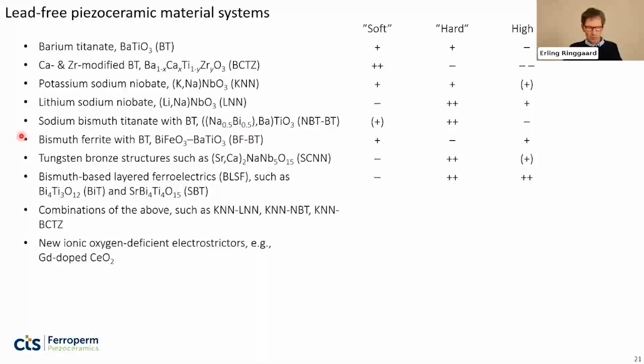Another interesting material is bismuth ferrite, also generally used in a solid solution with barium titanate, and I write it like this. Next material is not so well known. It's developed in Japan. It's a group of materials called the tungsten bronze structures, and one example is mentioned here. This is interesting for again getting very hard properties and a material that can be driven at very high vibration velocity. And some of these tungsten bronze materials can also be used for quite high temperature.